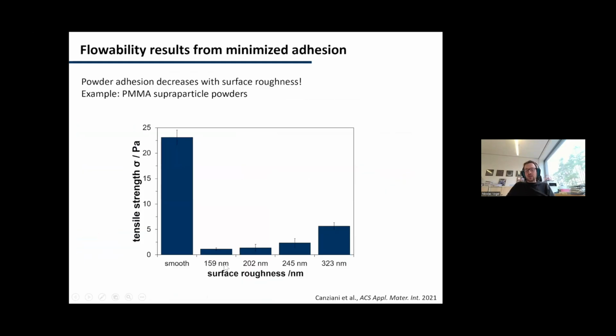So in a sense, the simple answer is because that was the smallest particle size that we could reliably make with the PMMA particles before they became so polydispersed that we couldn't determine the roughness fairly well anymore. If you would go down, I would expect it would be better, because the minimum that would be anticipated to make the smallest van der Waals forces would be below 50 nanometers or so. But in effect, this was already by far good enough to create a very well-flowing powder, and then we didn't really need to bother anymore. But it's a very good point. It would become better. That would be my prediction as well for even smaller particles.